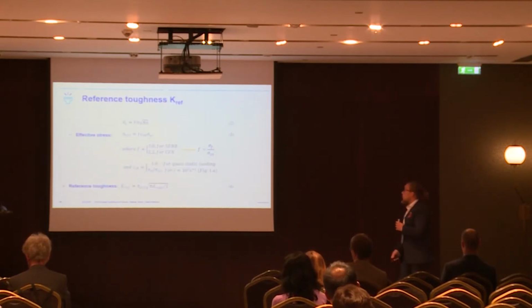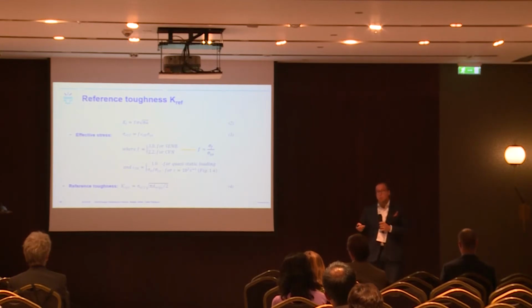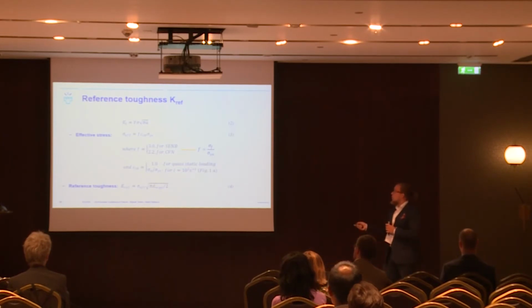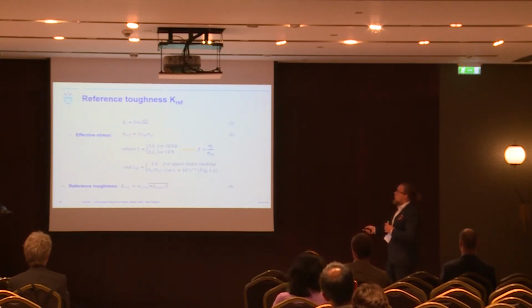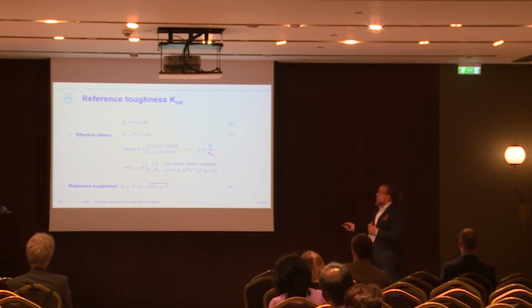So to jump into this reference toughness idea, we start with the basic K1 stress intensity, but now when we want to address both the cases with a notch and a sharp crack and have the same parameters, we need to modify the stress term. And with the engineering way to address this, we use coefficient F, which is the general ratio between the fracture stress and the yield stress.